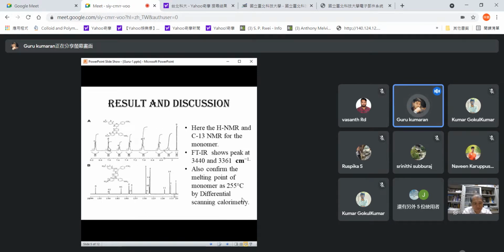This slide shows the characterization of the monomer by the proton NMR. The figure A shows the proton NMR of the monomer, which has 9 different protons in it, and figure B shows the carbon 13 NMR for the monomer, and the FTIR spectra shows the peaks at 3440 and 3361 centimeter inverse that show the presence of the amine group, and they also confirm the monomer's melting point as 255 degrees Celsius by the differential scanning calorimetry.